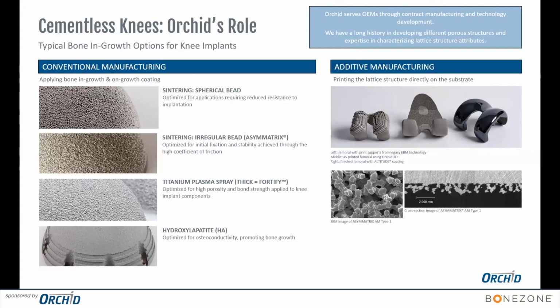Now, for instance, if you do not want that reduction, or you do not want the extent of reduction to be quite that low, then of course you would apply it using vacuum plasma spray. Right? What vacuum plasma spray allows is that it doesn't heat up the implant quite to the same extent. So your mechanical properties are really not affected quite to the same extent as you would if you were to do sintered coatings. So recently, Orchid Orthopedic Solutions, we have entered into the additively manufactured